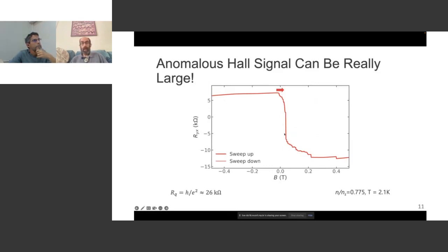He saw that indeed there's a pretty sharp transition in the Hall signal near when you go through zero magnetic field. And then when you come back, again, there's a pretty sharp jump, but these don't occur actually right at zero field. They're separated a bit. There's hysteresis. And so if you sweep the field and come back to zero, there's a memory of the history of this. And there are a few things that are striking about this. First of all, this is a signal that is not just based on the density of carriers and the magnetic field. It appears that it's affected by a magnetization.